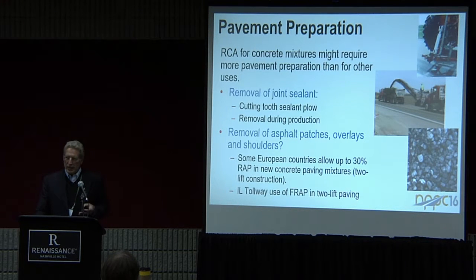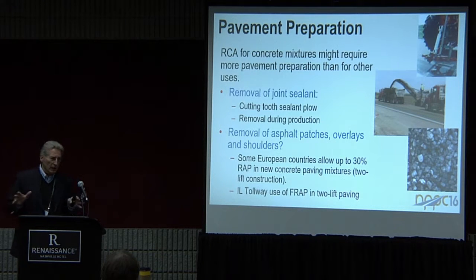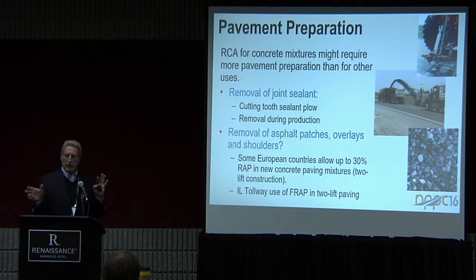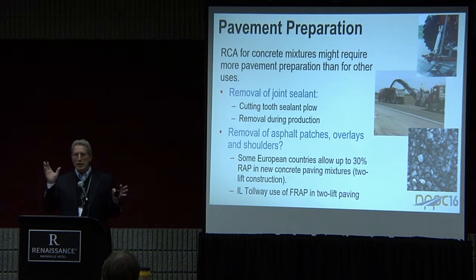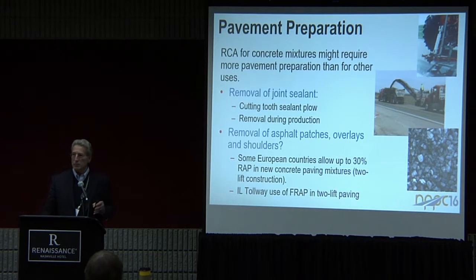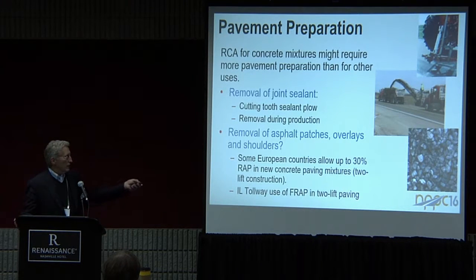And with the air entraining admixtures that they were using at the time, they had a hard time controlling the air content of their mix, because there's some kind of a chemical interaction going on between the air entraining admixtures and the recycled asphalt that was present. Today's modern admixtures, we don't seem to see that sort of a concern, and as a result, again, we see a lot of European countries, Austria, Germany, allowing up to 30% RAP in their concrete mix,